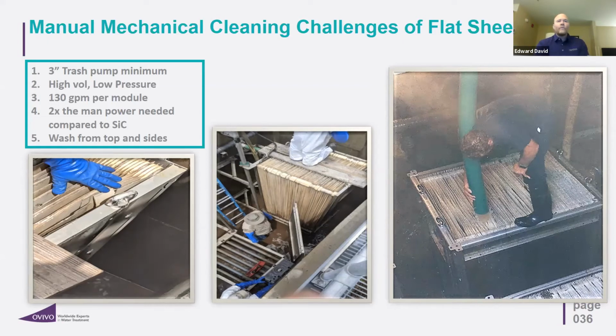And one of the toughest things to deal with that we found over time is it takes 130 gallons per minute per module. Doesn't matter if you have a 10,000 gallons per day plant or if you have a million gallons per day plant. It still takes 130 gallons per minute per module to clean it in up to 20 minutes. So if you have your system down and you have to fix the dewatering issue and remove the dewatering, not only are you not permeating water, you're putting a lot more water back into that system. So it is very, very challenging.